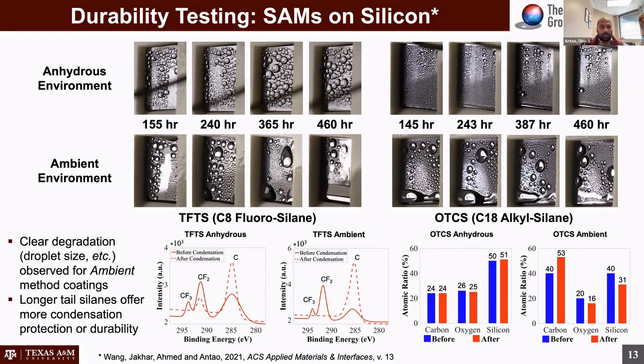And so aspects that we observed in the fluorosilane was that in the ambient environment, so the uncontrolled environment, you completely lost all the fluorosilane from the surface in the regions that you can see as film-wise condensation. And in the anhydrous environment coating, you tended to lose some of your silane molecules, but not a lot of it.